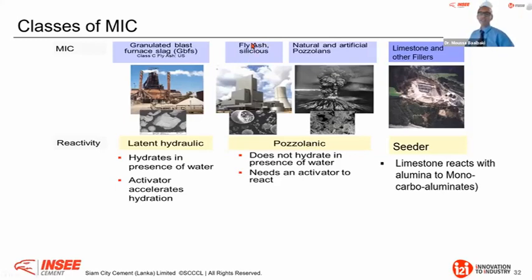Some activators work very well with them, like lime. Lime is a byproduct from the hydration reaction of clinker, portlandite. Therefore, if you put lime with this product, you will develop strength. And this is what our ancestors have done during Greek time, during Egyptian time. If you look at how we have built the Pantheon, how we have built the pyramids, the technology is just like that. They take aluminum silicate, activate it with lime, hydrated lime, and they get strength.